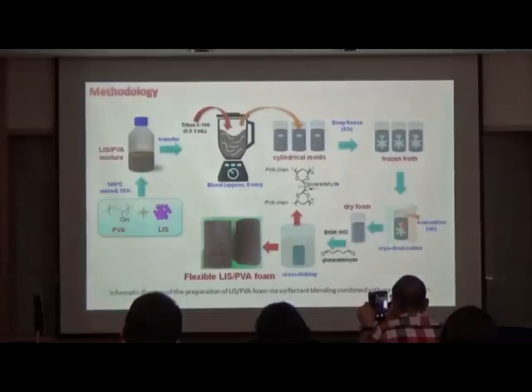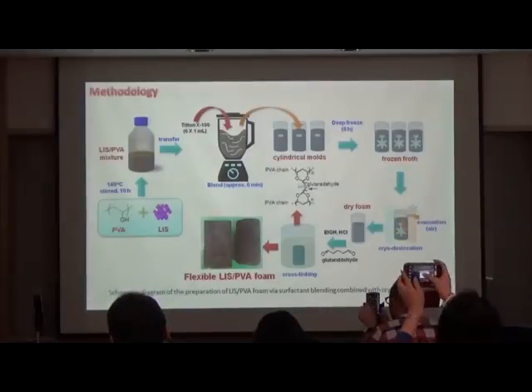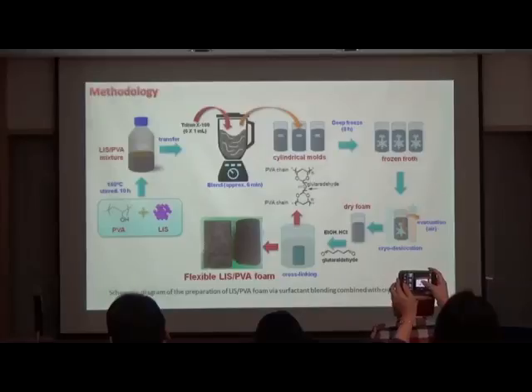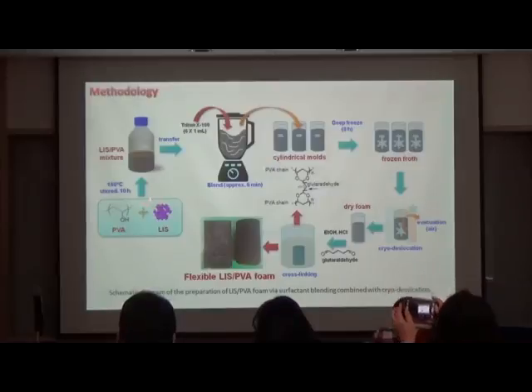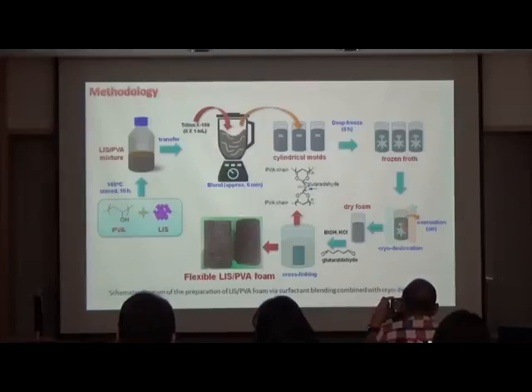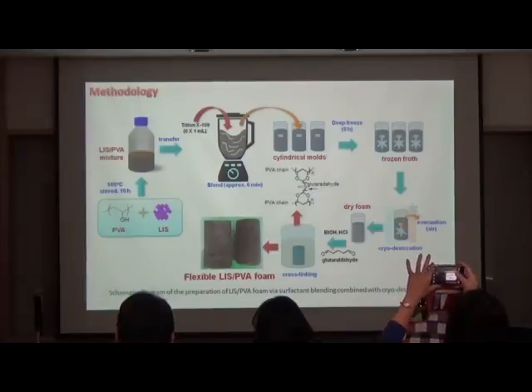Now, the preparation of the composite foams is shown in the following figure. First, the dope solution with different LIS loadings was prepared by initially dissolving the PVA in deionized water with constant agitation for 6 hours at 140 degrees Celsius. For a particular LIS loading, a known amount of LIS was added and then further stirred for 4 hours. The dope solution is then transferred to a blender. A froth dispersion is produced by alternate blending and addition of non-ionic surfactant, polyoxyethylene octyl phenyl ether or Triton X100, to the dope solution.